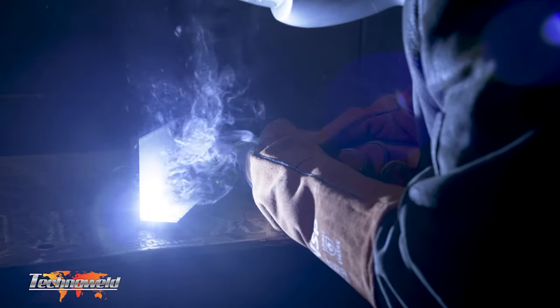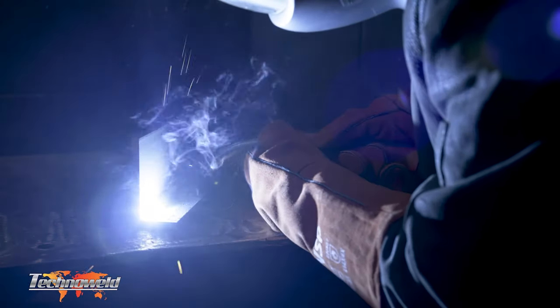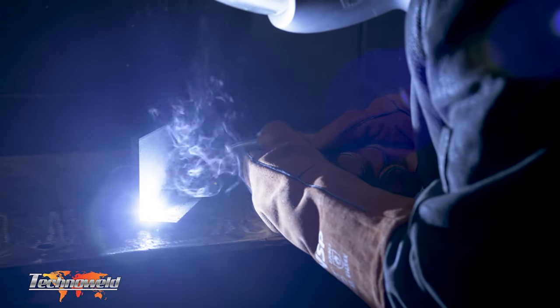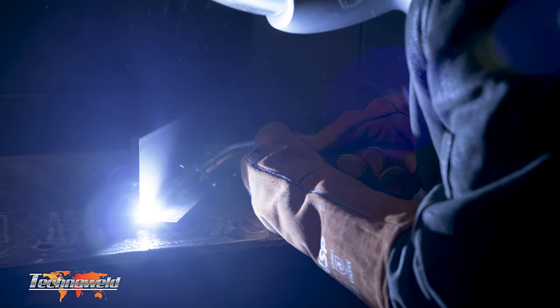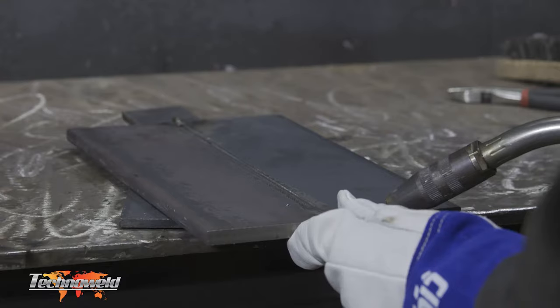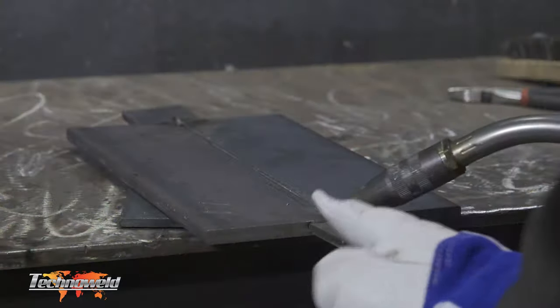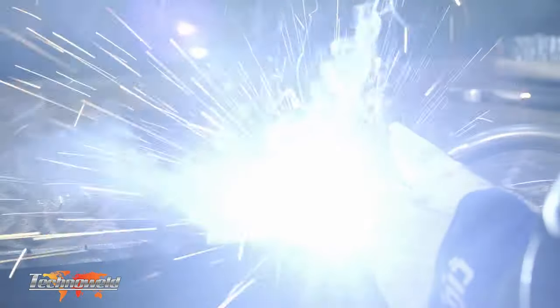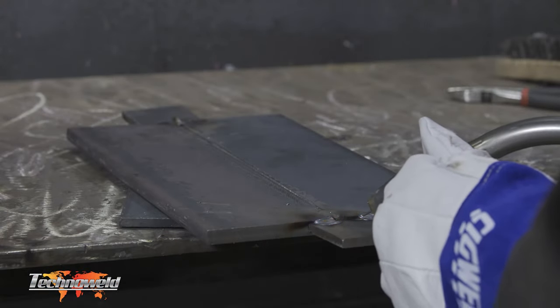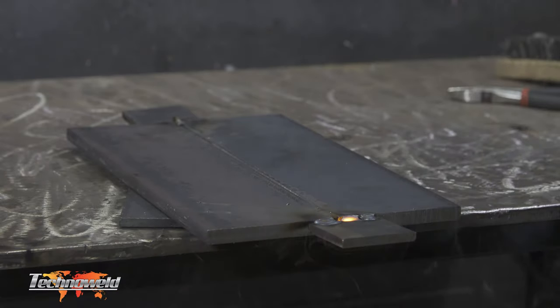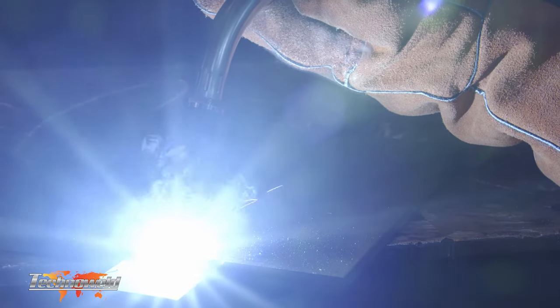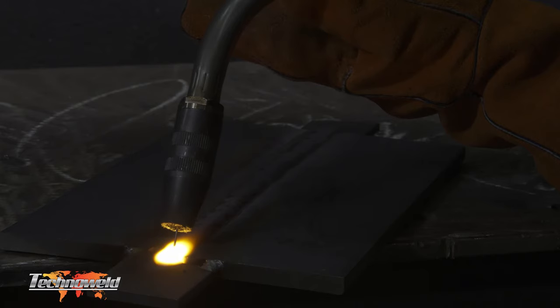This bar example is relevant in any circumstance when we apply heat to metal, whether it's a bar, plate, or pipe. If we don't allow for expansion and contraction of the material we will end up with distortion. With welding we have more than one piece of metal we have to consider. Typically there are three elements to consider: two pieces of metal that are being joined together and the weld metal itself. Distortion forces will affect all three of these elements. As weld metal volume increases, the amount of force or load increases and so does the amount of distortion. More weld, more distortion.